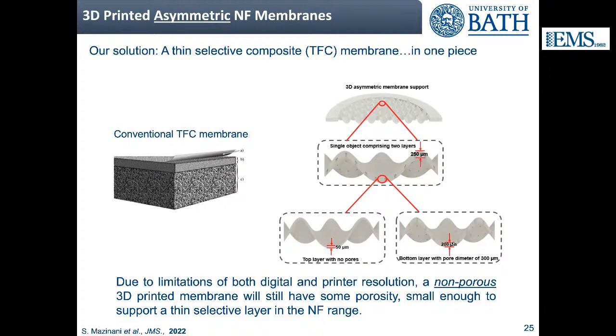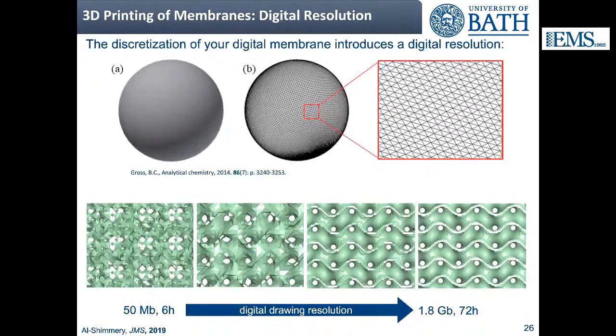And let me explain a bit more. You will remember what I showed you at the start, that the digital resolution of the membrane affects what gets printed. If you look at these images at the bottom, this is the same object, but at the left you have a much lower resolution, and you see a lot more white spots, which are essentially porosity, than you see on the right, where it is a much more uniform structure.